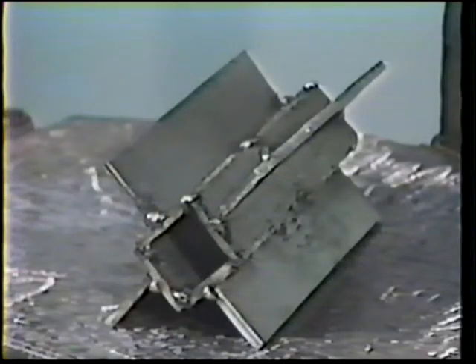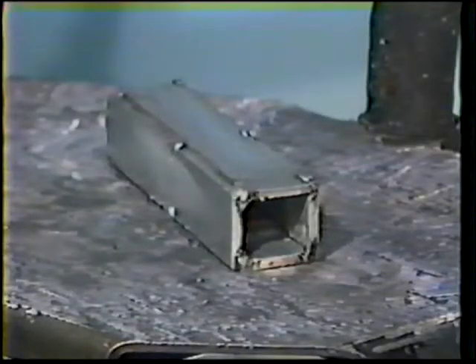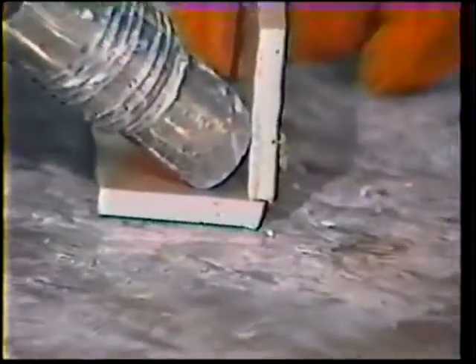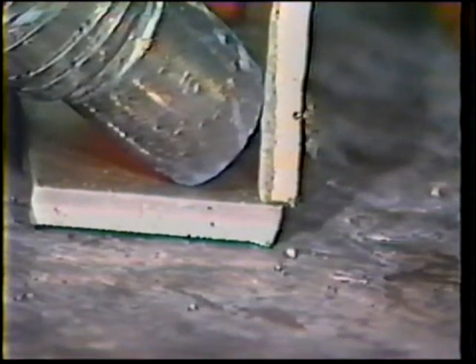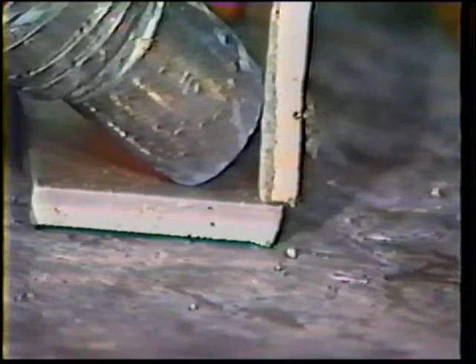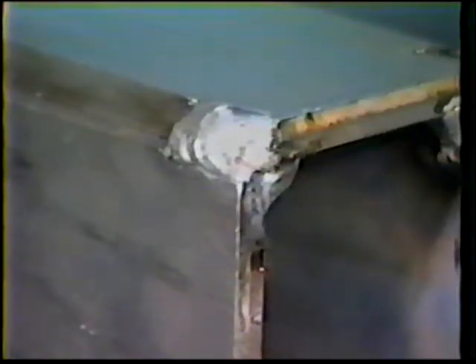The workpiece for this job practice is an 8-plate assembly, which forms 4 corner joints and 4 T-joints. The corner joints will each receive a single pass, and all T-joints will be welded with a total of 3 passes. To construct the workpiece, first, assemble 4 of the plates to form a box. The edges should be overlapped about 1/16 inch to produce the desired corner joints. Deposit small tack welds in the corners and at the center of the joint to hold the plates in place.